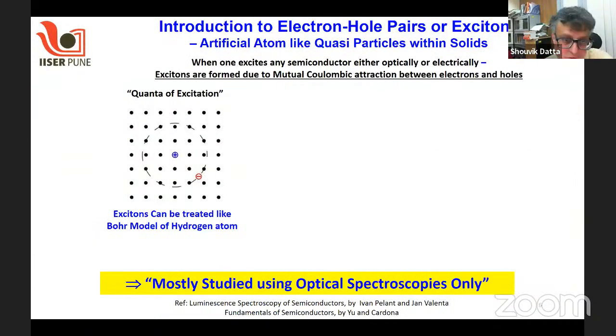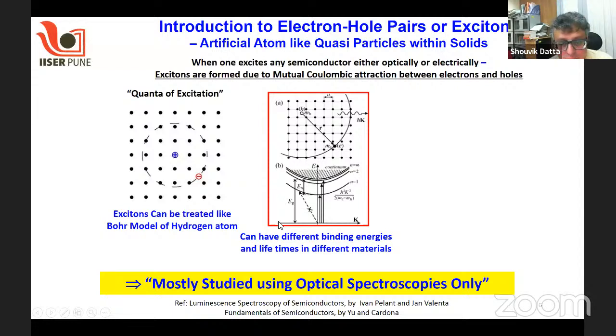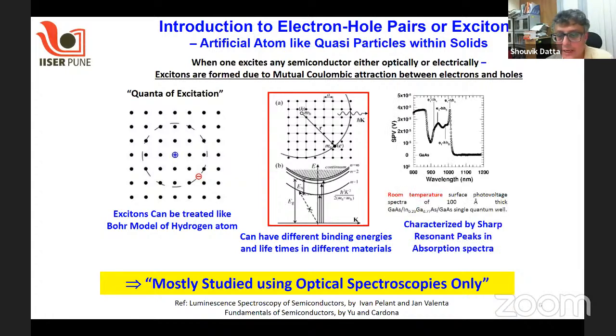Okay, so what are excitons, for people who are not familiar with them? Excitons are artificial atom-like quasi-particles within a solid. When one excites semiconductors either optically or electrically using forward bias, electron-hole pairs are created within the semiconductor structures, and those electrons and holes face mutual Coulombic attraction and form hydrogen-like bound states. Most of the time, these bound states have different binding energies and lifetimes based on which material you are choosing. Usually, spectroscopically, these are identified by sharp resonant peaks in the absorption spectra. And so far, people mostly study excitons by optical spectroscopy only.